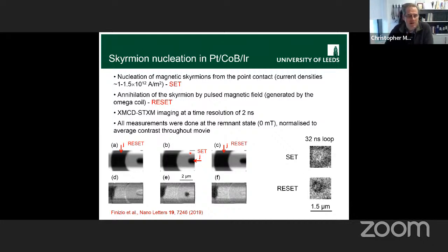So, here we can see it working. If we look at these three images, it's now on its side. Here's the tip of the finger, and here's part of the coil. Here it is in a uniformly magnetized state. Then we inject what we call a set pulse through the finger, and we've now got this patch of dark contrast. That's a skyrmion that was created by the current pulse. Then we put a so-called reset pulse through our coil, and it gives us this uniformly magnetized state back. And then we can do that over and over again to look at different conditions, or look at the dynamics.